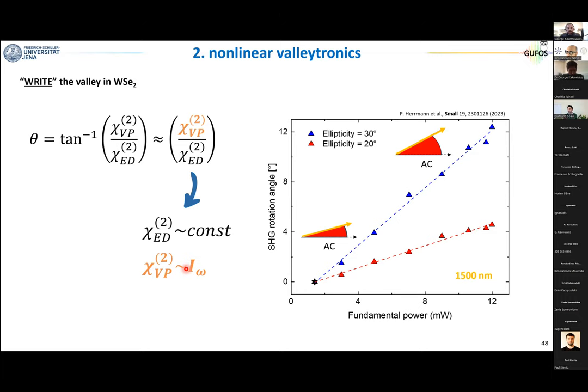So for this reason, as we change the intensity of the power that we shine on the sample, we change also the rotation angle because we induce a larger valley imbalance. And it turns out that the scaling of this term with the fundamental power is linear. And I'm not going into the details. If you're interested, we can discuss this in the question session. This is a clear indication that we break time reversal symmetry by the coherent optical Stark effect. So not by a real excited state population, but by an off-resonant and ultra-fast coherent process.